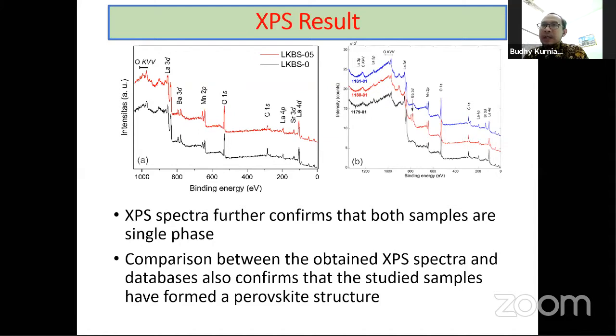And then the XPS result. The spectra confirm that both samples are single phase, as justified from the XRD. Comparison between the obtained XPS spectra and databases also confirms that the studied samples have formed a perovskite structure. Our sample is a perovskite structure, and from the XPS result, we can justify this structure. Next, please.